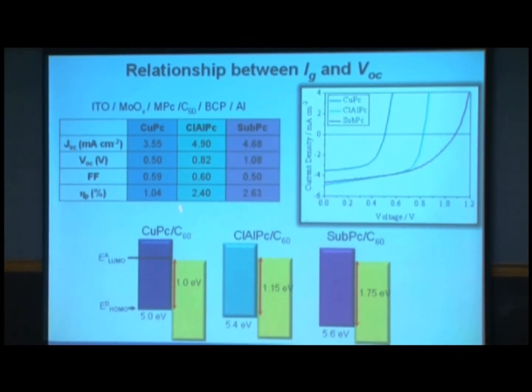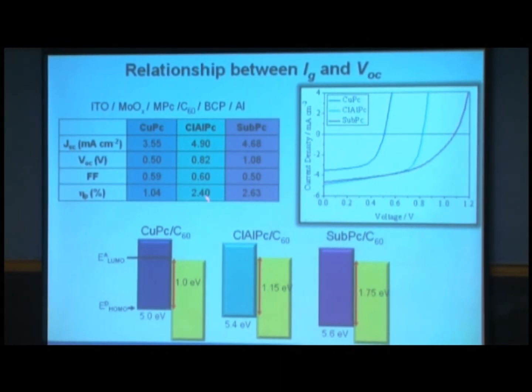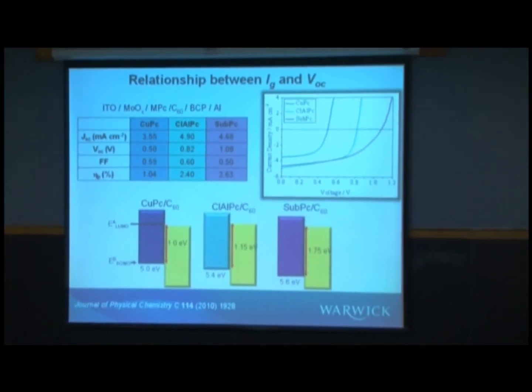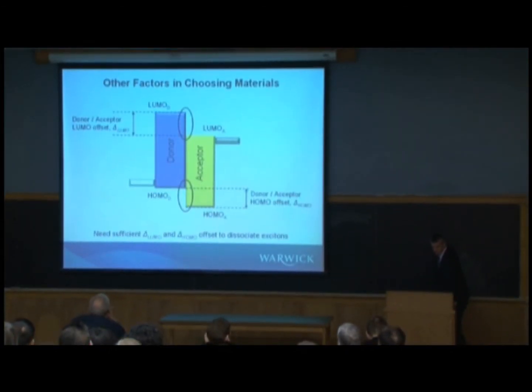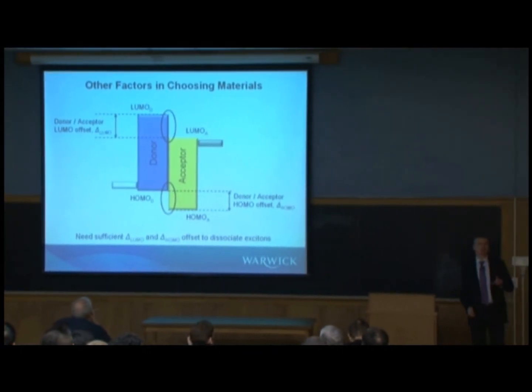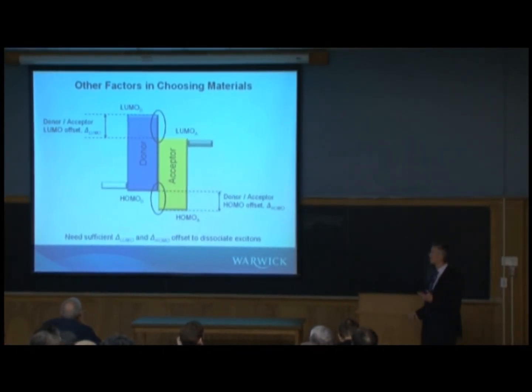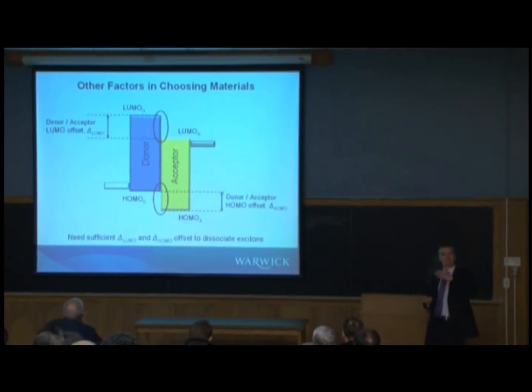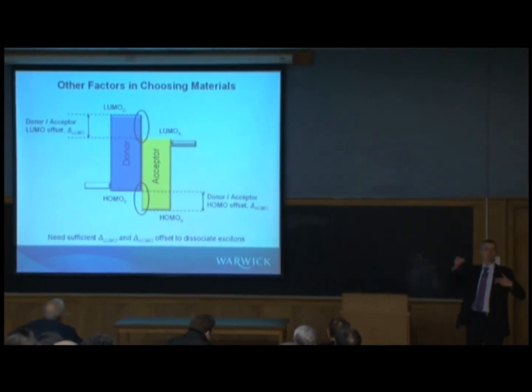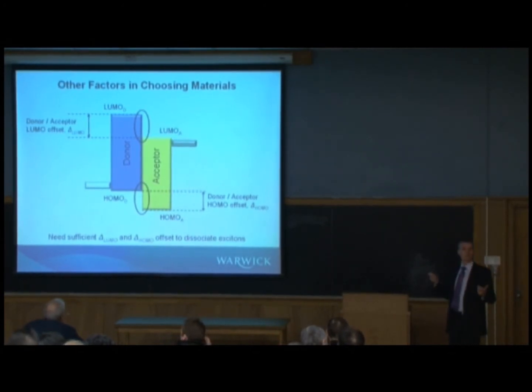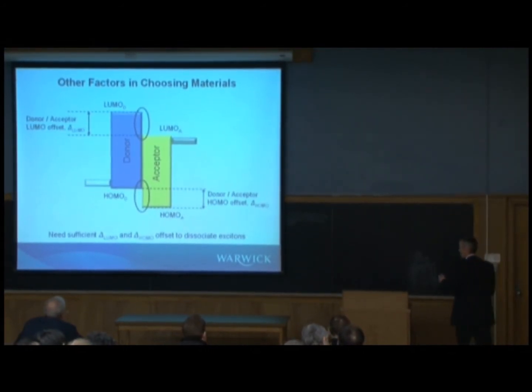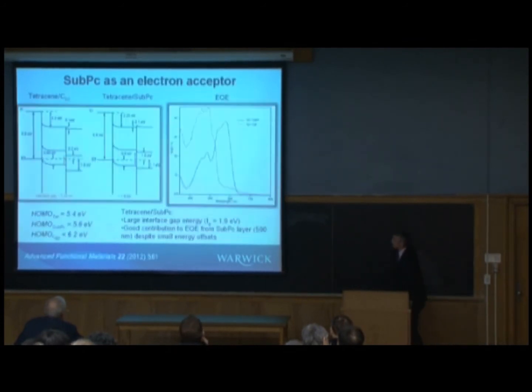You can see 1 eV yields a voltage of 0.5. Out here we have a 1.75 eV interface gap energy, and we're only extracting a voltage of nearly 1.1 volts. So there's some very significant losses that you need to try and overcome to enhance the voltage. Now, as I said, you want to maximize the interface gap energy to maximize your voltage, but you can't just keep doing that because you'll sacrifice the offsets needed to dissociate the excitons. So again, it's this compromise between these energetics.